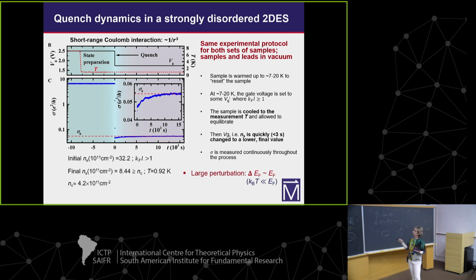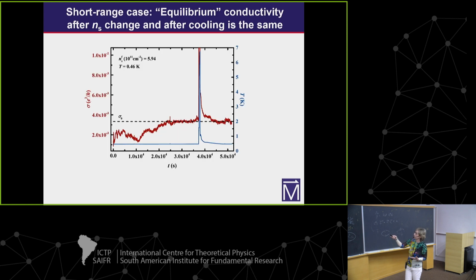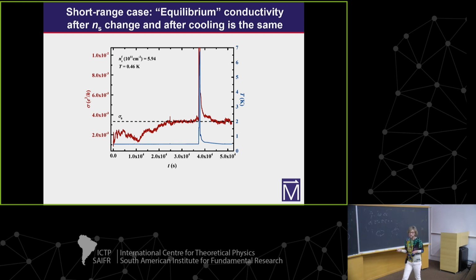Again, this is a very large perturbation. And at the end of this process, just like before, we warm the system up to some high temperature, cool back down again. We see that we reach the same value. So this tells us that we waited long enough for the system, or conductivity, to reach some steady state.